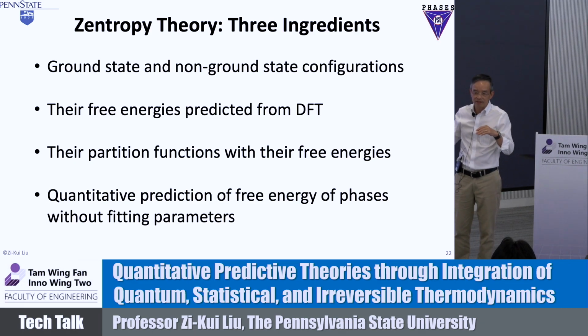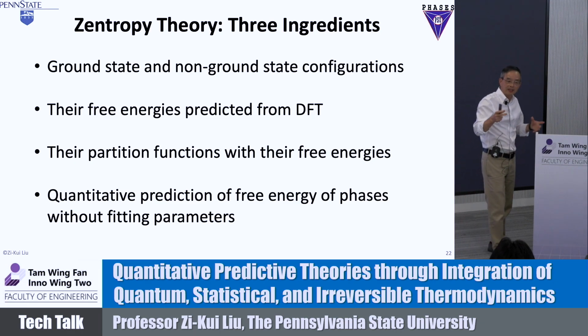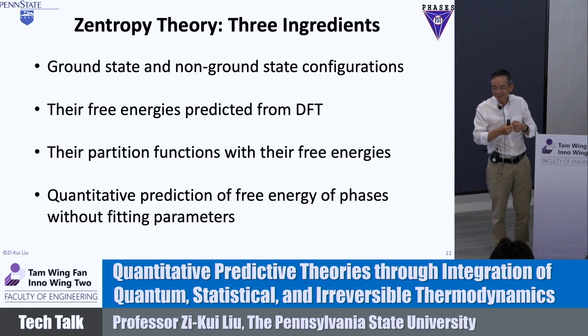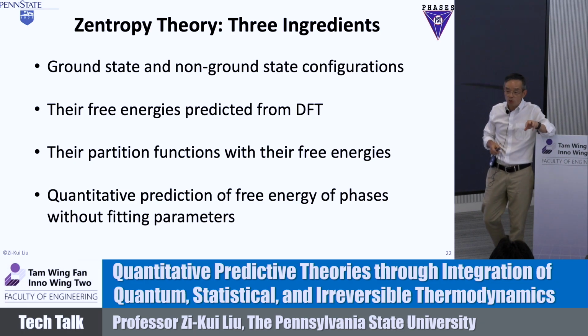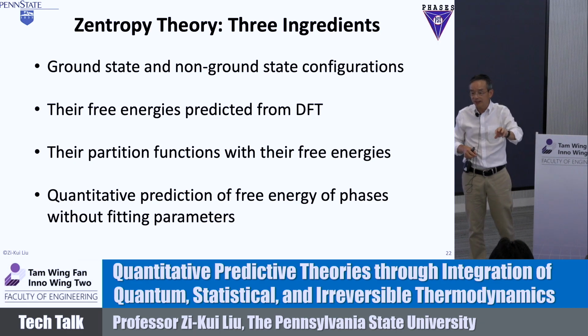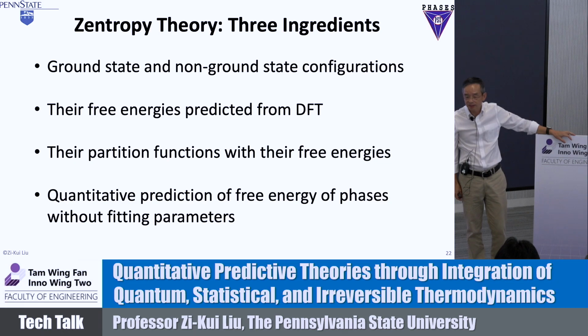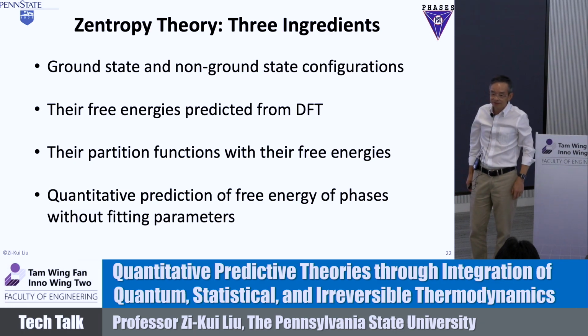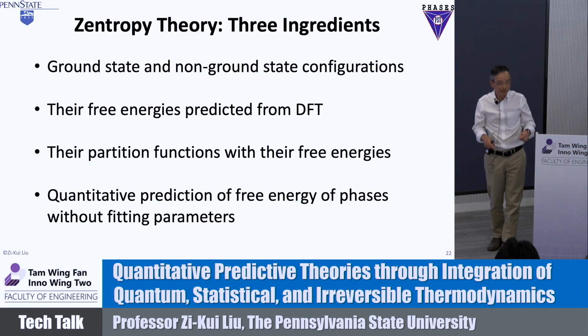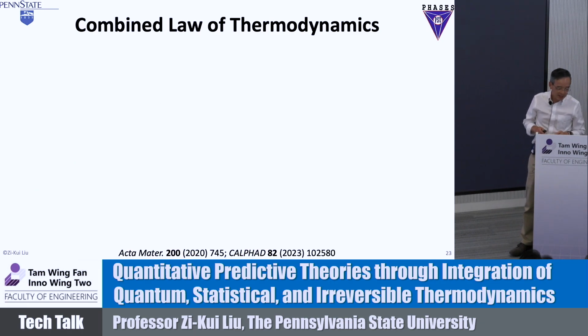If you look at the entropy equation there, right? The low scale is statistical. The high scale is deterministic. But in order to get the deterministic outcome, you have to get started with statistical, stochastic. I hope the entropy actually unified them together. That's why the entropy has two terms. One is a quantum mechanical term. That's purely statistical, right? And then you have the probability one, which is larger scale probability. But when put together, you got the heat capacity measurement. Isn't that amazing? Heat capacity is deterministic. Any material, like you measure in the lab, you get the same heat capacity every time. You never get a different heat capacity if you do the same material, right? That's deterministic. All right. So we did that all right.